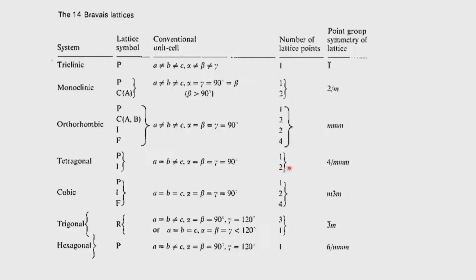and 2, and the maximum symmetry associated with the tetragonal system is 4/m 2/m 2/m, which is simplified and written as 4/m m m. Obviously, we cannot have a combination of this kind. It has to be 4/m 2/m 2/m, which will have both primitive and inversion associated with it.